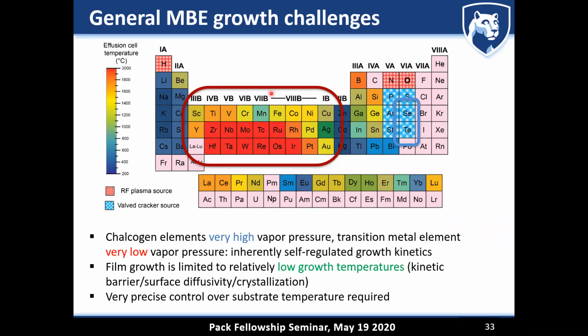And particularly, this very high vapor pressure of the selenium and the tellurium forces you to lower your growth temperature. And that means that you're impeding your growth kinetics. There are going to be kinetic barriers, surface diffusivity, and even the crystallization temperature might be too high compared to the growth temperature that you're applying. So really, you have to go all the way away from what you've done in the oxides, where typical growth temperatures are on the order of 800 to 900 degrees C, and push it way below 500 degrees C.